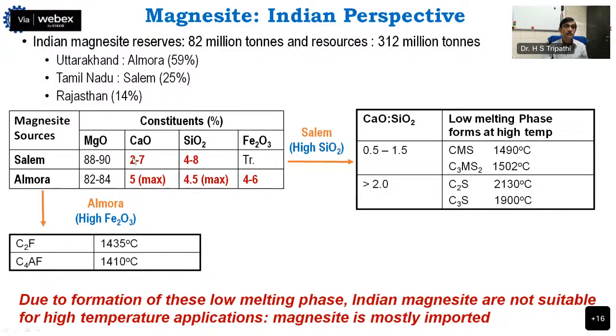So what happens if you heat treat this, because this refractory will be used at much higher temperature, maybe around 1650 to 1700 degrees centigrade? When you heat this magnesite to get the sintered magnesia, it will form different types of low melting phases. So this is monticellite, merwinite, but if the lime silica ratio is more, then some high melting phases are formed: dicalcium silicate, tricalcium silicate.